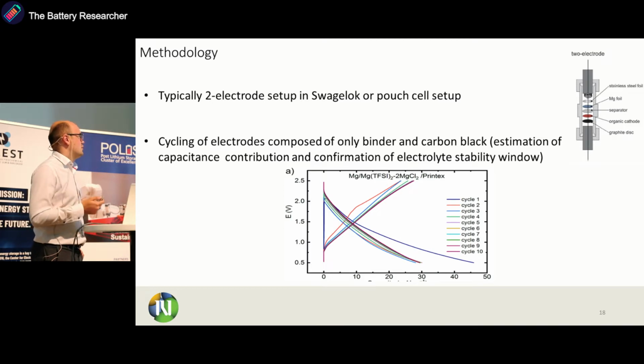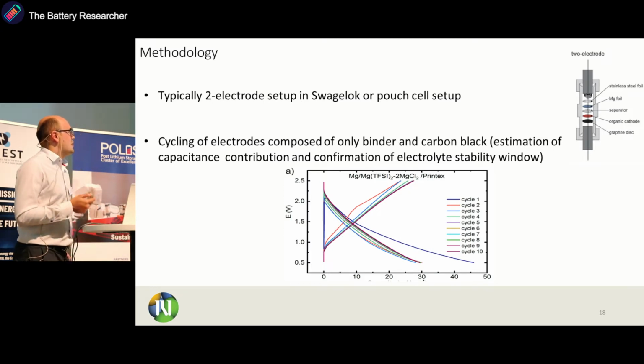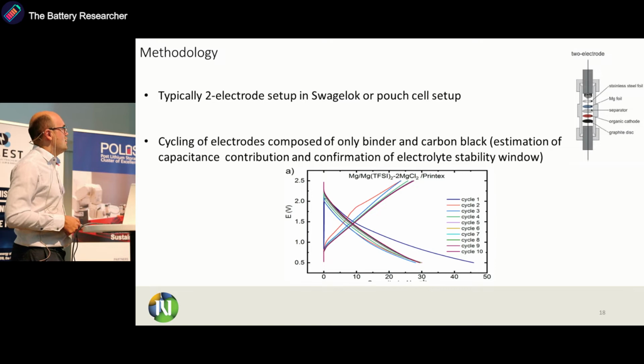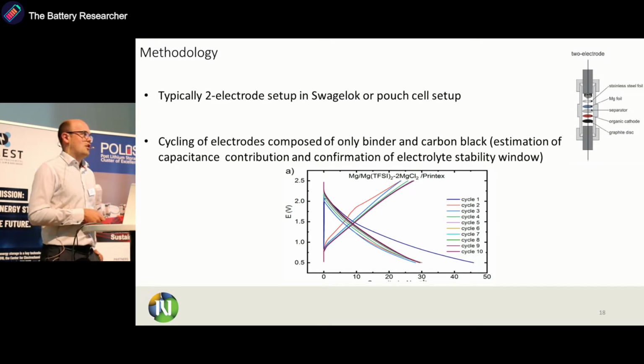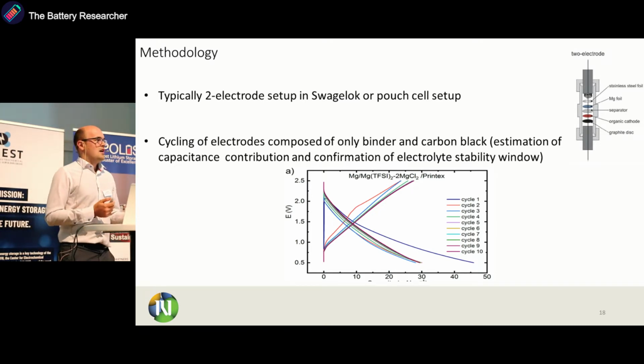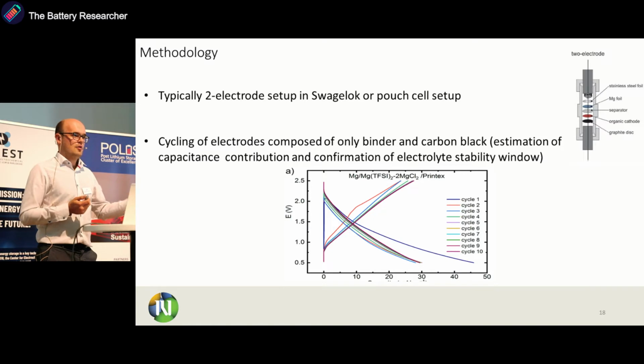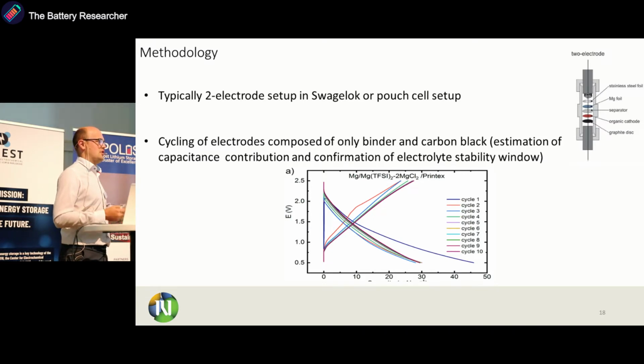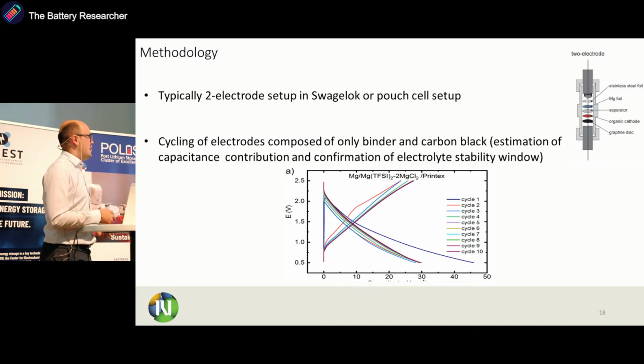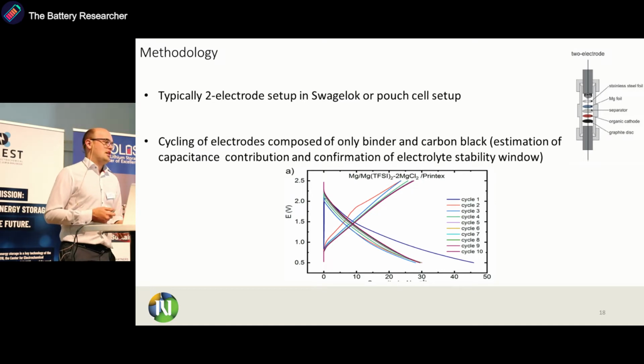And one thing which we find also quite important, because in the organic field quite a lot of carbon black is used, is to cycle plain electrodes. So electrodes composed of only binder and carbon black, to see their capacitance contribution and to probe for side reactions. Because often when you see electrolyte papers, they are done with low surface area electrodes, metal like platinum, aluminum, but then when you employ high surface area carbon electrode, you have a lot more side reactions. So this is one of the ways to really estimate how much of side reactions you will have.